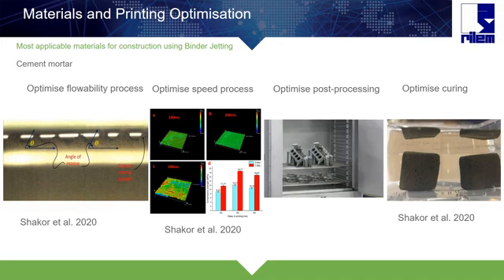Another thing it is necessary to check, especially for materials and printing optimization, is the flowability of the material. So we specifically need to optimize the flowability process, such as checking the angle of repose. We have checked the angle of repose for both the cement mortar materials and the gypsum, and they are quite close to each other.